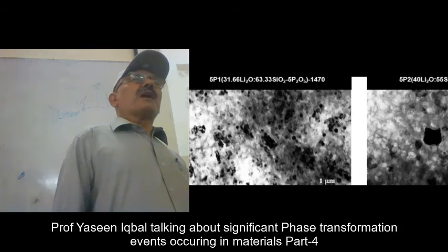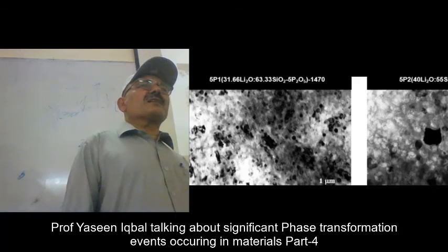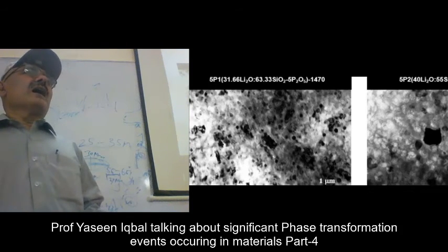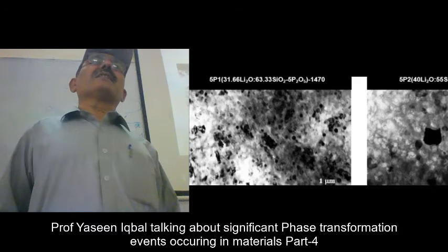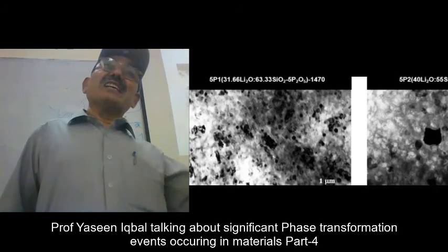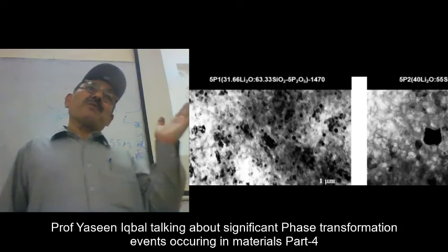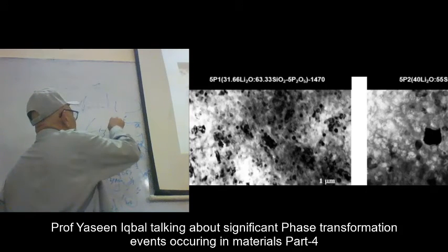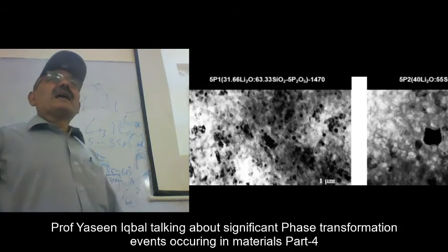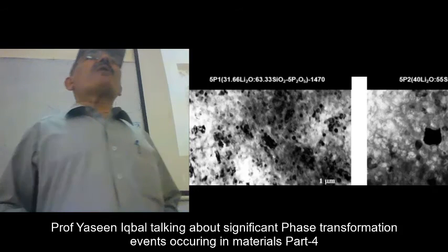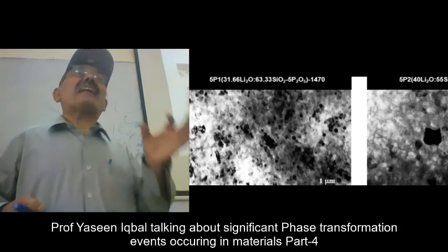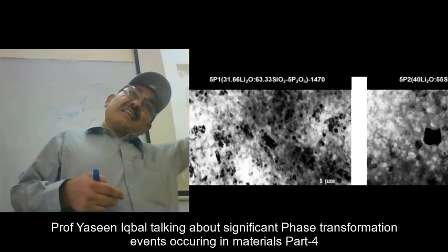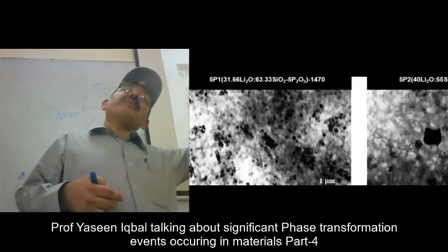I was looking to find, as you remember, I told you yesterday that phosphorus pentoxide made the crystallization easier by first forming the lithium phosphate, Li3PO4, crystal nuclei, which provided epitaxial crystallization sites for the crystallization of the matrix phase.